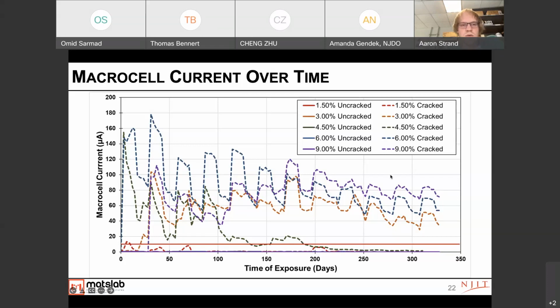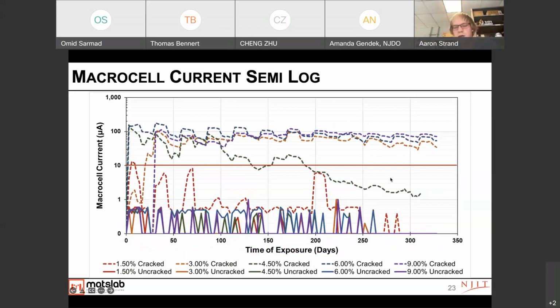So moving into this slide, this is the same as previous, but just showing that the uncracked specimens stayed very much lower than the actual threshold that we were looking for the macrocell current. And this again indicates that at least through testing, there wasn't any corrosion that was likely present within these specimens at the end of testing.